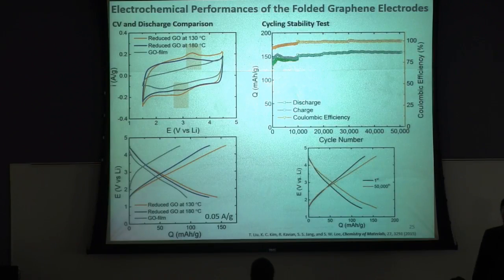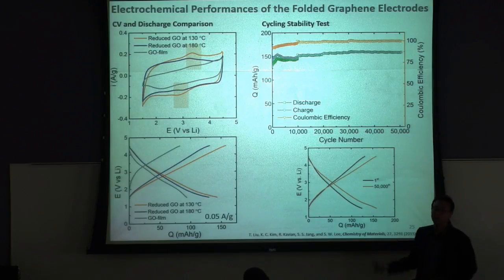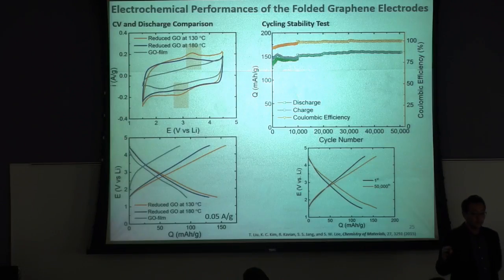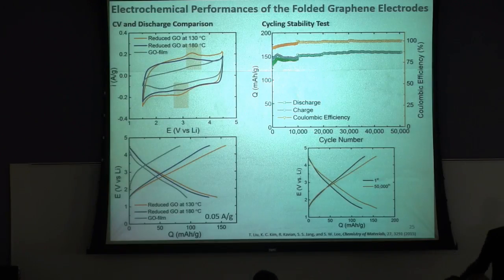One distinct advantage of this organic material is high cycling stability. We did cycling tests up to 50,000 cycles, and actually there is no capacity degradation. Actually, the capacity is a little bit increased. This is the first cycle, and this is the 50,000th cycle charge-discharge curve. As you can see, the capacity has increased. This is because, I guess, during the charging and discharging process, electrolyte ions can diffuse into the deeper side of the electrodes and find more electrochemically active surface area.